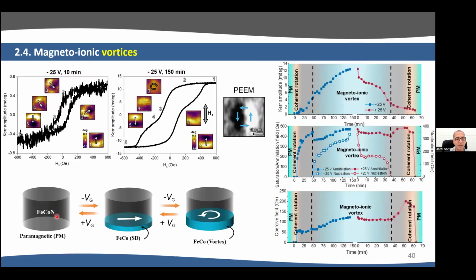And what happens here, the idea is that we start with paramagnetic state off. So we have a Magneto-Ionic switch like before, but tuning the kind of reversal. So we go from paramagnetic state to single domain state for thin iron cobalt. And then as the iron cobalt thickness increases, we form this vortex. This vortex state is a state in which the spins just follow the edge of the structure. So if we do MFM, what we would expect is at some point to lose the magnetic contrast.